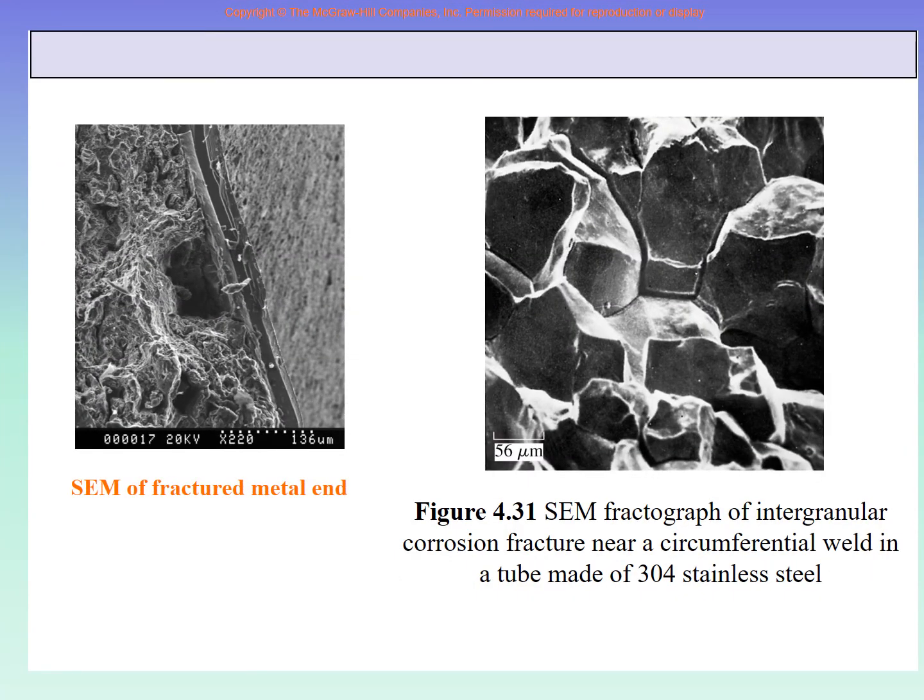And we are showing you some images. We took a piece of material that was fractured, right? We took, say, a tensile test, fractured it, or we took the impact test and fractured it. From the fractured surface, we take a very small piece, and then we see how the fracture actually happened. Here we can see the different grains, and we can see that the fracture is on the grain boundary, or it is through the grains and so on.